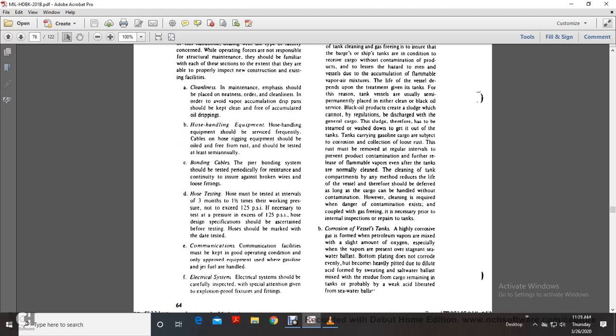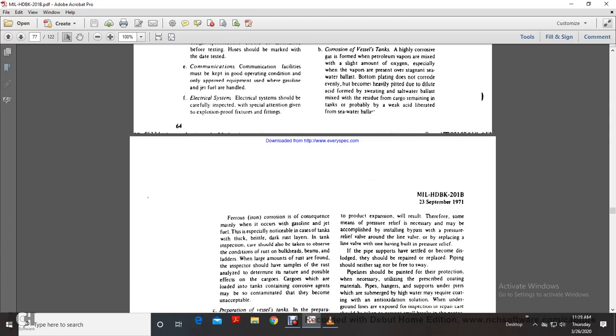Alright, corrosion of vessel tanks. Highly corrosive gases in the form of petroleum vapors are mixed with a slight amount of oxygen, especially with vapor present and stagnant seawater ballast. Bottom plating does not corrode evenly, because of heavy pitting due to dilute acid formation. Sweating water ballast mixed with the residual cargo remaining in the tank probably liberates a weak acid from the seawater ballast.